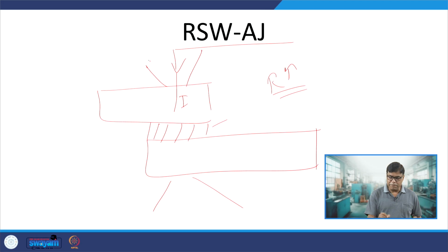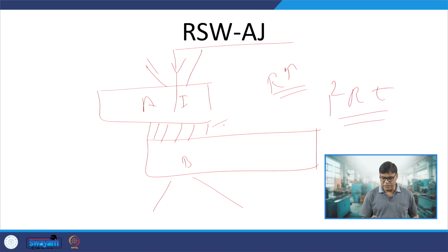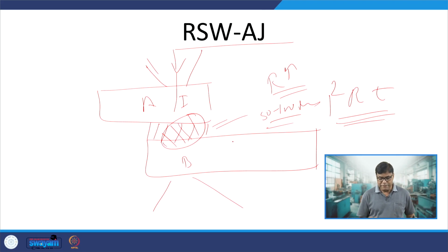So, under pressure, current is allowed to flow from sheet A to sheet B across this adhesive through I squared RT heating, because this thickness is very small, maybe 50 to 100 micrometers. Through the I squared RT heating, heat is generated, and that helps in development of the metallurgical joint. And the heat generated is large, because we certainly need the melting of the interface surfaces of the two metallic sheets which are being joined by the resistance welding.